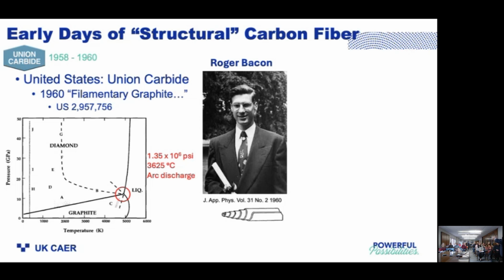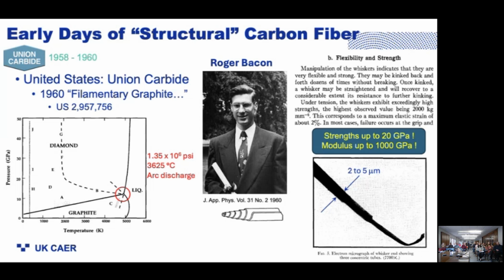He described breaking open one of those electrodes, and it looked like Christmas tinsel with all these little whiskers of graphite. He took those out and began to study them, and found that he could take these little whiskers of graphite and kink them back and forth, and they would bounce back. He was able to test them in tension and found the tensile strength of these to be something around 20 gigapascals.